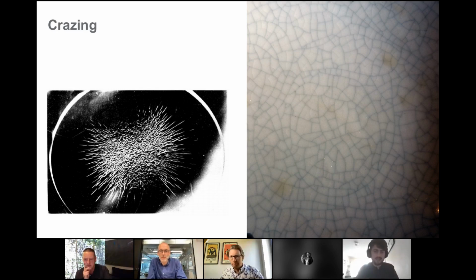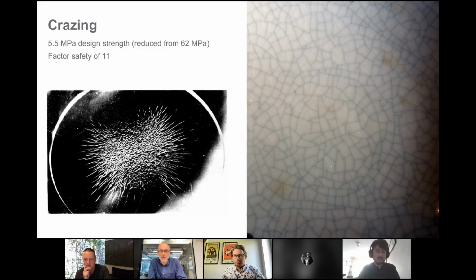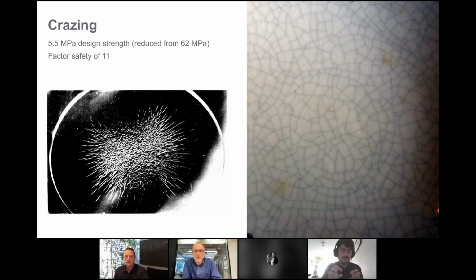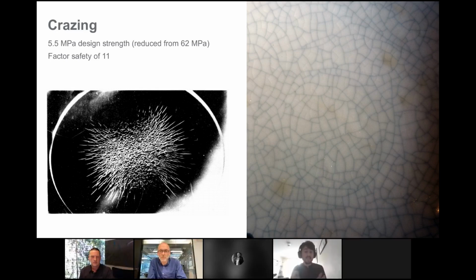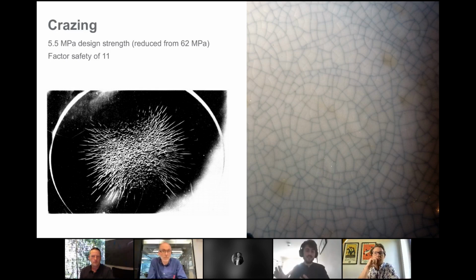So what does this mean in terms of design? Well, crazing happens under a number of different scenarios, one of which is tensile stress. If it's being stretched, pulled apart, you'll get these little micro cracks forming on the surface. And this happens at a much lower stress than the stress that would break it. So instead of designing to our original 62 megapascal tension stress, we were actually designing to a much lower stress of 5.5 to make sure that this whitening effect doesn't happen.